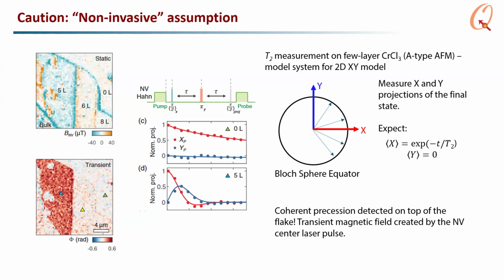Also, the NV center is always considered a non-invasive technique in theory, but that's not always true. Motivated by these theories, we tried to look at noise in few layer chromium chloride, which is a model system for the 2D XY model. The 2D XY model should have a BKT transition with magnetic vortices and magnetic anti-vortices. So we tried to do the T2 noise relaxometry on these samples, and what you expect to see is the X projection of the phase get diminished, right?